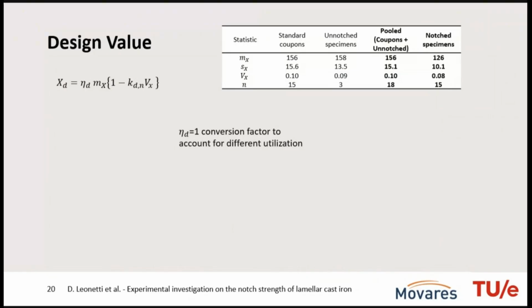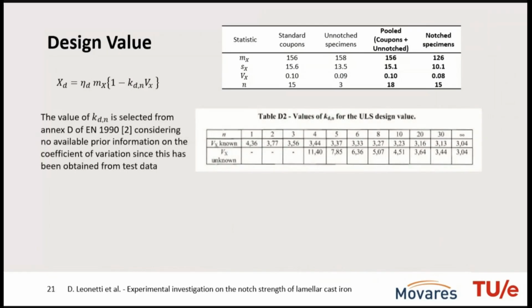But if you consider a hollow column in bending, well, we can imagine that on the wall thickness we could imagine something like a uniform stress distribution. So eta for us is equal to 1. And then there is this kappa value, which is related to the non-central Student distribution, and we see two options in the Eurocode, in case the standard deviation or the coefficient of variation was known or unknown. Well, we are in this case, and depending on the number of specimens that we tested, we picked the interpolated value here for kappa.